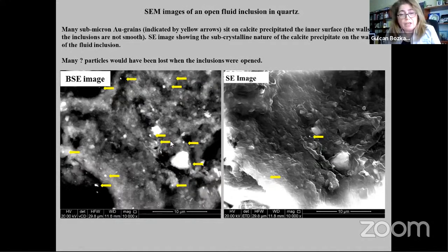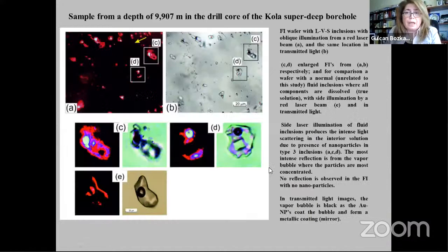In a high magnification image of the interior of the open inclusions, we can see numerous particles smaller than 1 micrometer attached to the coating of calcite in the inclusions. There are other minerals also present, but gold is always rounded and the brightest phase. There are obviously a large number of these particles in the inclusions. In the fluid inclusions from the Arapçandere deposit, the gold particles were reasonably large colloidal particles.